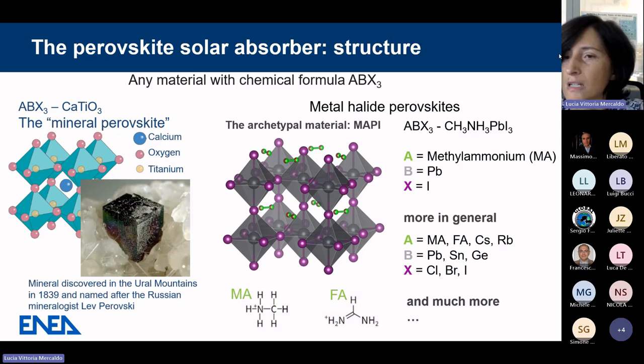On the right-hand side, we see the structure of the archetypal material, the methylammonium lead iodide, with the methylammonium cation occupying the site A, lead occupying site B, and the X site occupied by anions, in this case iodine. But more in general, the metal halide perovskites in PV present many other combinations in the sites A and B, and also several options for the anions of chlorine, bromine, iodine.